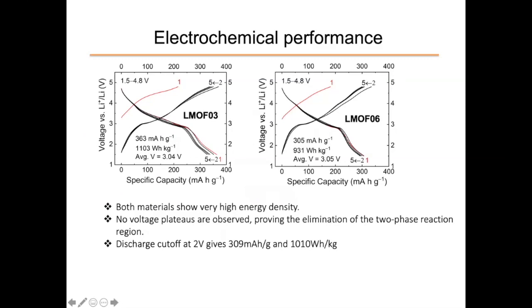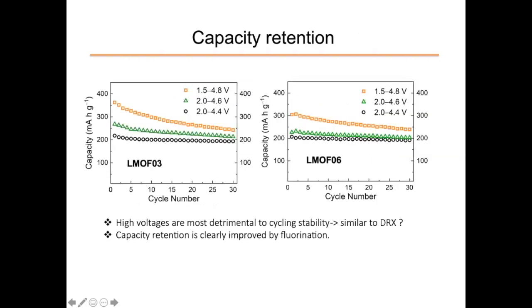And they work really well. Here are the cycling curves of these materials. We get, again, over 300 milliamperes per gram, approaching 1,000 watt hours per kilogram. Even when we do a cutoff at only 2 volt, we still get over 300 milliamperes per gram and 1,000 watt hours per kilogram. So these are becoming very high energy density materials.